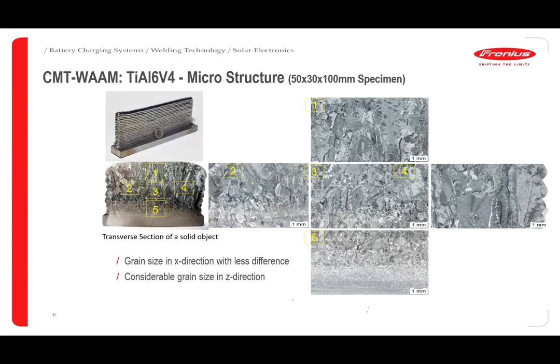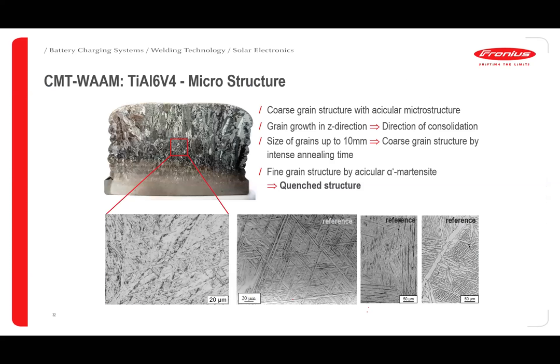Okay, in front of your slides, you'll be able to see a wall which is made out of this wire, which is the titanium wire, where you can see the layer which is manufactured and the microstructure. So you can see 1, 2, 3, 4, the grain sizes in various areas. The only issue is you will be seeing on the next bigger magnification a very, very coarse microstructure, which is a kind of acicular microstructure. And you can see the grain growth in various locations in Z direction, which are like a needle-like shape, which we call an alpha prime or alpha martensite kind of structure.